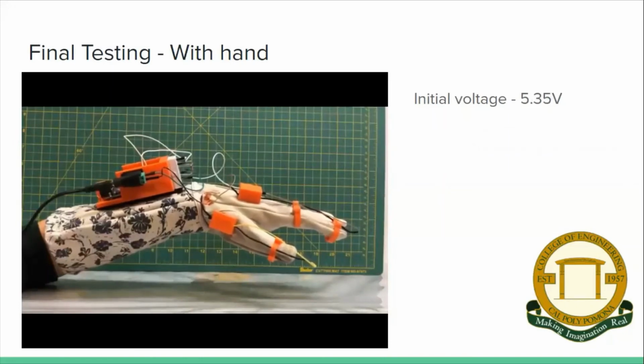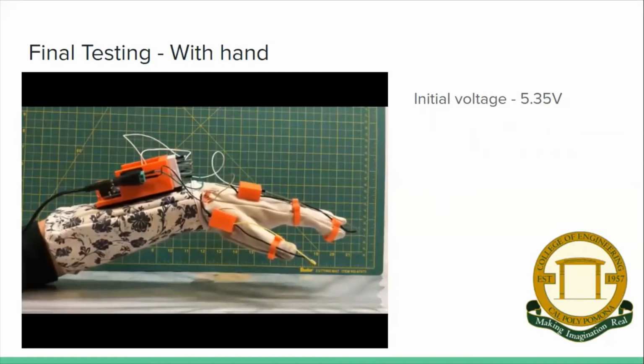The initial voltage was measured at 5.35 volts. This final testing we did was with a hand in the glove. We found that the actuation was a much slower process with the hand inside the glove, since the hand naturally wanted to oppose the force of the actuation.